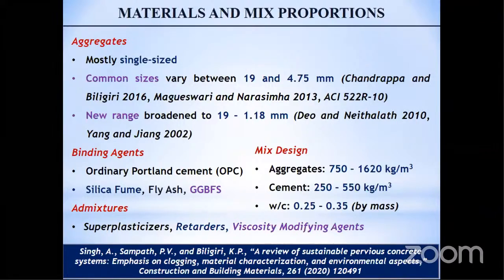The most common binding agent to create this pervious concrete material is ordinary Portland cement. Some other agents such as silica fume, fly ash, and GGBFS may also be used. The whole idea of introducing those materials is to create a denser matrix as compared to the conventional PC, which would ultimately result in higher strength characteristics. The typical water cement ratio varies between 0.25 and 0.35 by mass. However, some people report it as high as 0.45. But based on laboratory investigations, we have found that a water cement ratio close to 0.3 along with a superplasticizer gives us the best results in terms of strength as well as permeability.